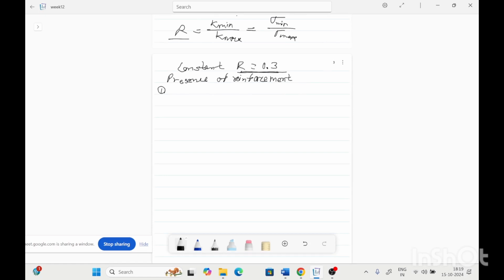Yeah, so for a constant R value of 0.3 and in the presence of reinforcement, the threshold will be high. Means the delta K threshold is high. Means for the same crack length, the alloy will fracture easily, but the composite will not fail. Means the threshold value increases for the composite.